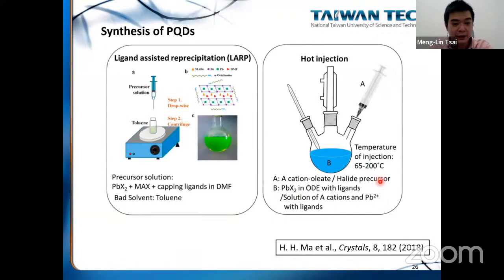These are the two main synthesis processes for this type of material, perovskite quantum dots. One is ligand-assisted reprecipitation. We first dissolve our precursors into a solvent and mix them, and then we put them into another anti-solvent, so it will reprecipitate inside this solution.